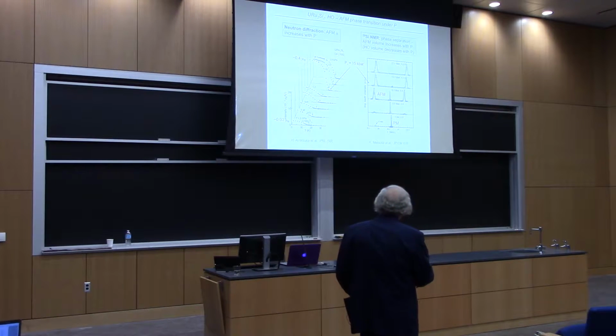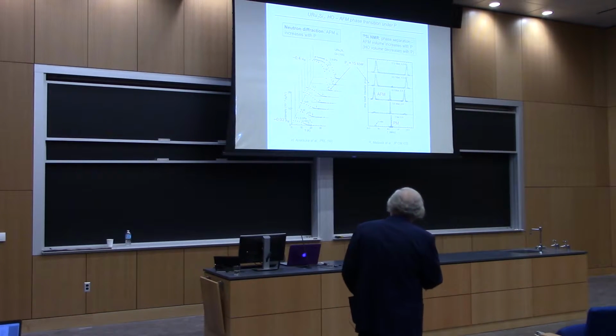magnetons. And this appears to be an average moment that you measure, because when you look at silicon-29 NMR, work by Matsuda and co-workers, you find that at atmospheric pressure there's a large signal due to the paramagnetism, very small signal due to the antiferromagnetism that's responsible for this small moment. And then as you apply pressure, the antiferromagnetic contribution increases at the expense of the paramagnetic contribution. Then when you reach 15 kilobars or 1.5 GPa, it's all antiferromagnetic.